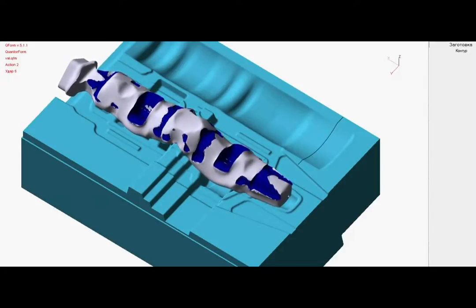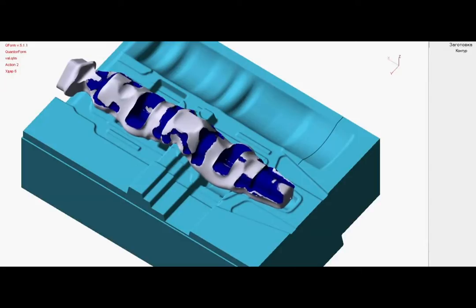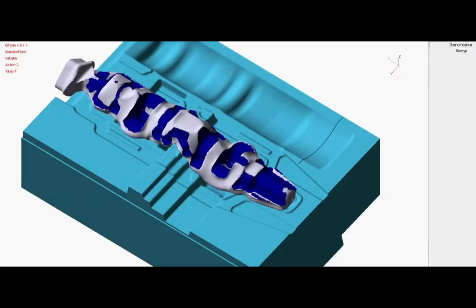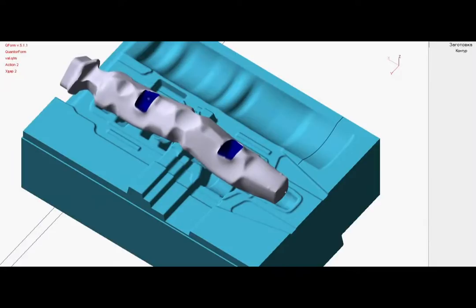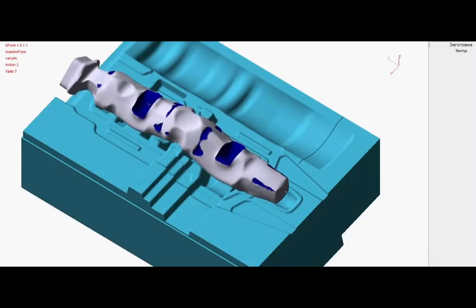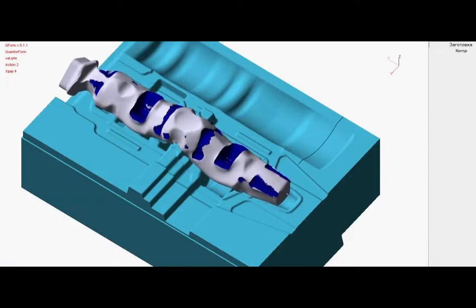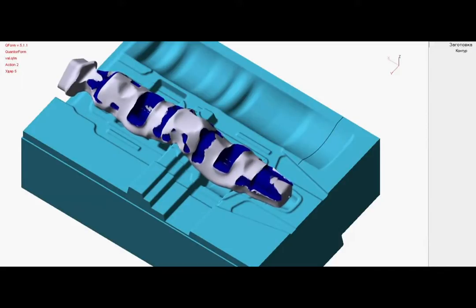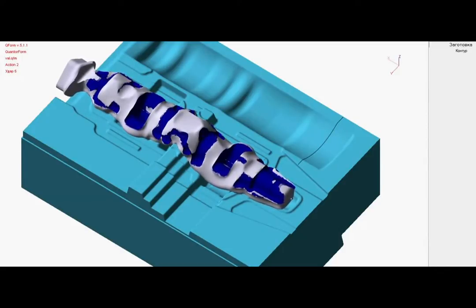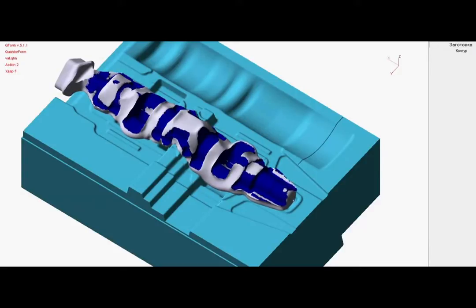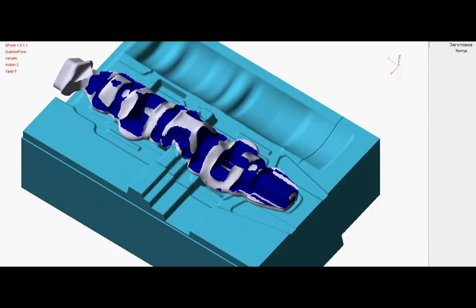in the previous video. Since closed die forging is not like flashless die forging, it's not absolutely sealed. Extra material will squeeze out when the two dies close together, which will form what we mentioned before, the flash. Here you can see the gray color indicates the flash, and there's also still some flash inside the die mold. Actually, the flash will be removed later, usually by a trimming process.